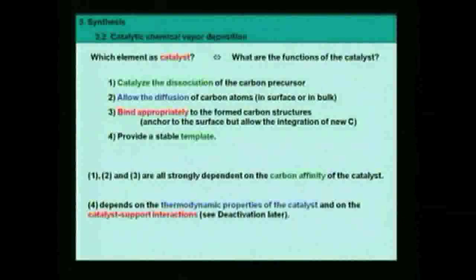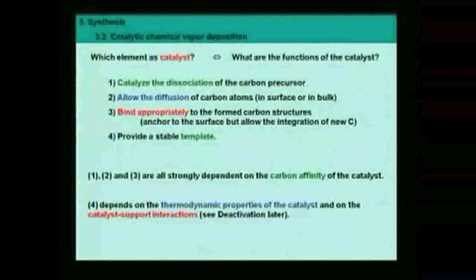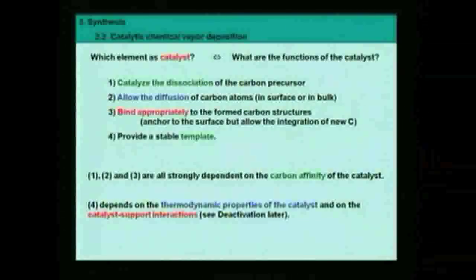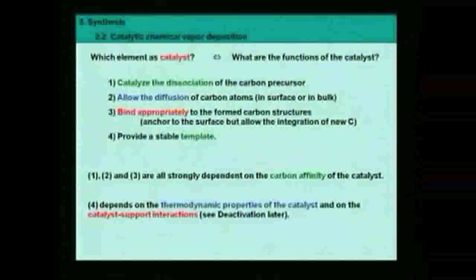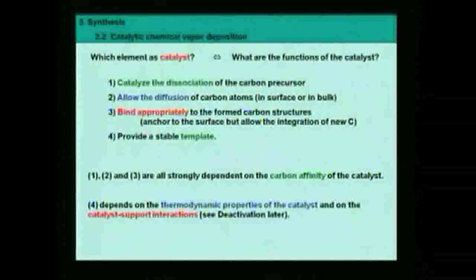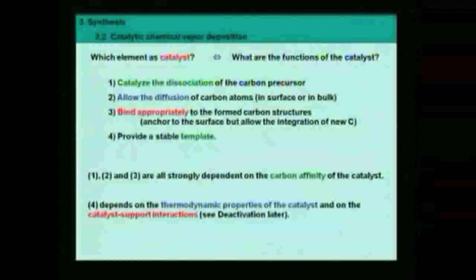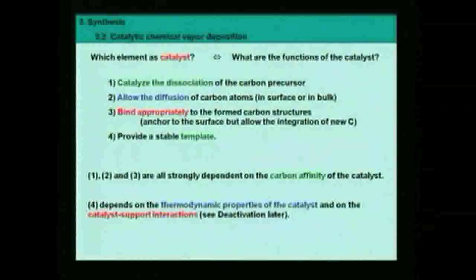Points 1, 2, and 3 are strongly dependent on what we call carbon affinity. This means the affinity of an element to bind to carbon. And we will see many examples of how carbon affinity shows up in different reactions. Carbon affinity is important because the higher carbon affinity makes the best catalyst for decomposition. Carbon affinity is also important because a too strong carbon affinity will prevent diffusion of carbon atoms at the surface.